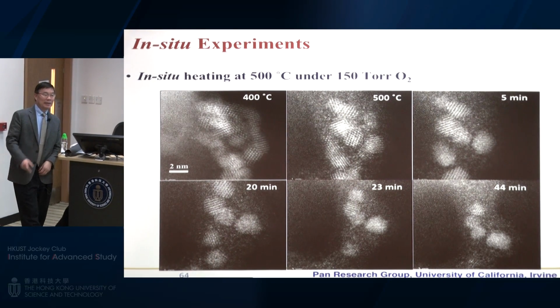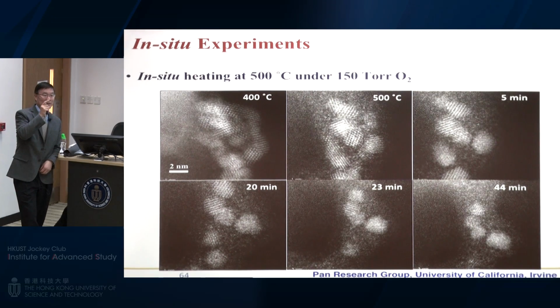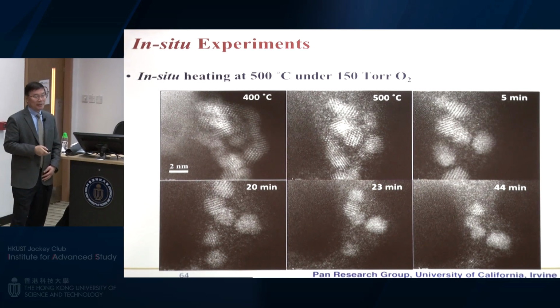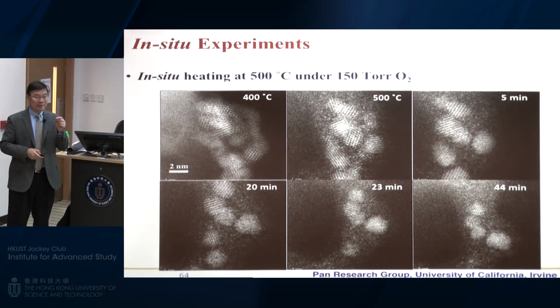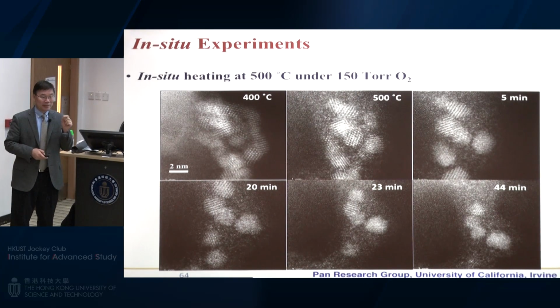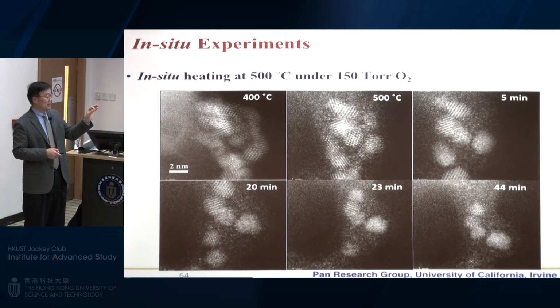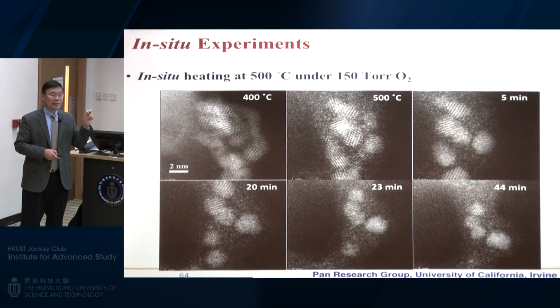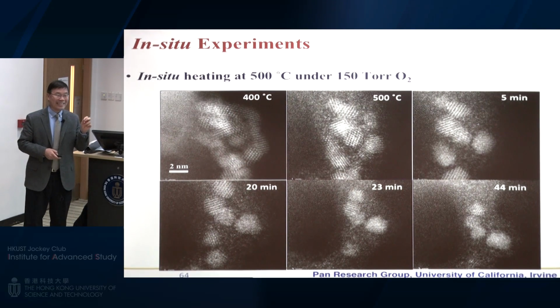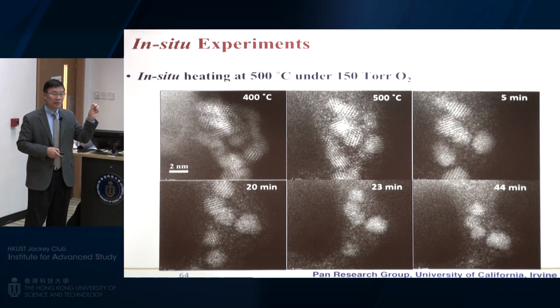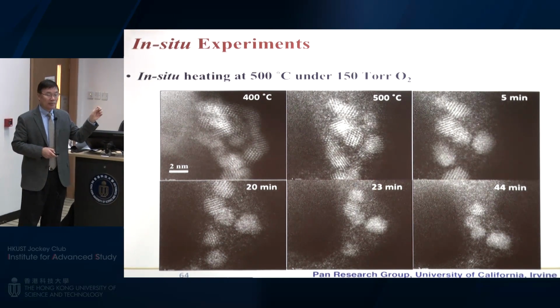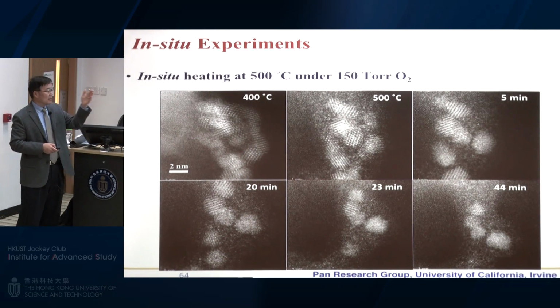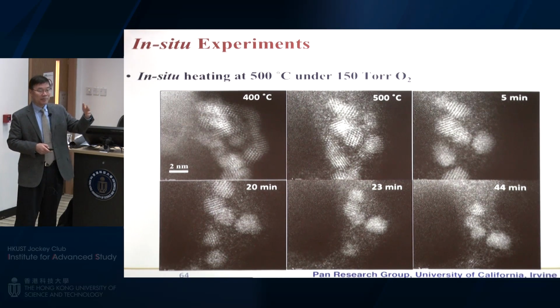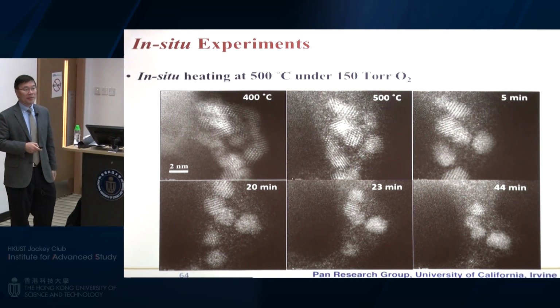We don't know. I gave one slide to compare E10 with a high atmosphere pressure holder. With E10, the advantage is that you can have a mass spectrometer built in the system. But in our current version of this gas cell, we do not even have EDS. They are upgrading our facility next month. Technically you can do EELS, electron energy loss spectroscopy, to determine chemical state, but the membrane is too thick. Multiple scattering is still a problem. So EDS will be a good way.